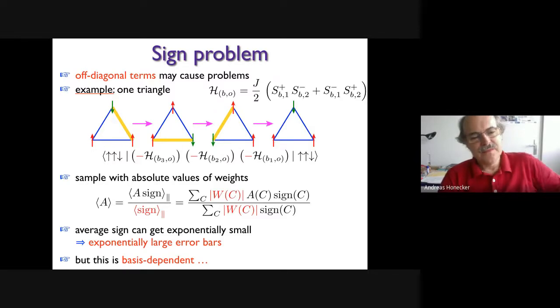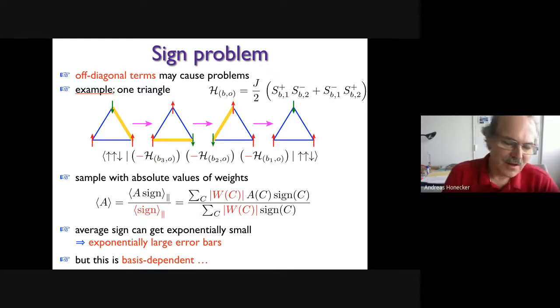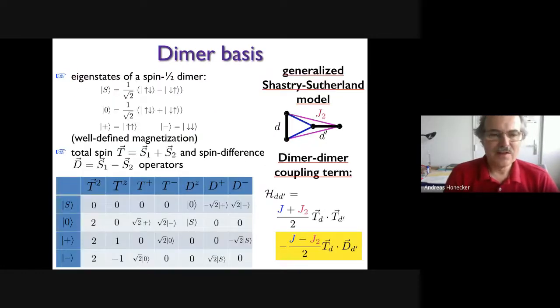So you sample with respect to the absolute values, but then in the measurements you have to restore the sign. You can run the code in that way, but the problem is that the average sign can get exponentially small, and it usually does get exponentially small if you have a sign problem. If you try to estimate error bars for an exponentially small quantity, they are relatively exponentially large. And that means you get exponentially large error bars. But, and this is the good news, this finding is basis dependent. So you might have a chance to do better by changing to different bases.